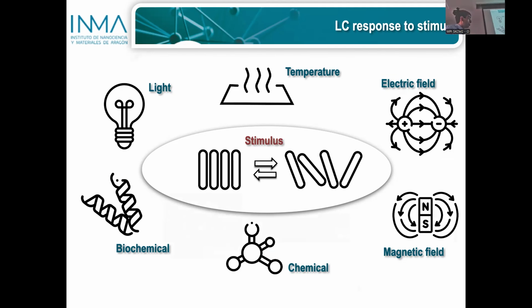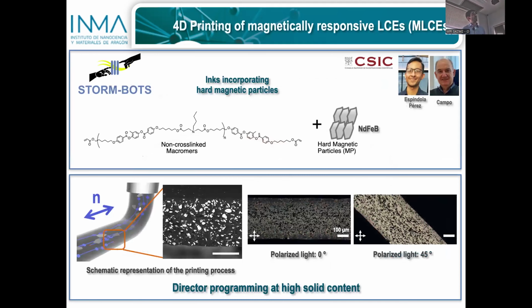So we first go to magnetic materials, and this is a collaboration that we did with Javier Campo, also an affiliated member of this institute, in which we included hard magnetic particles in our polymers, and by appropriate dispersion we can generate an ink that can be printed, and we can maintain the alignment of the liquid crystal despite the high load of magnetic particles.